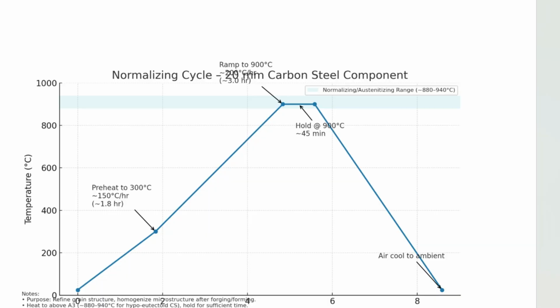Here, the only difference with annealing is that this treatment is not cooled in a furnace. There is no furnace, right? So the temperature gradient is more rapid because it is happening in the air. There is no controlled cooling in the normalizing process, which is done in the annealing furnace. Now, it will cool down rapidly in open air. So here also, you are refining grain size, but since it is cooling faster, you will have more toughness and slightly harder structure compared to annealing.